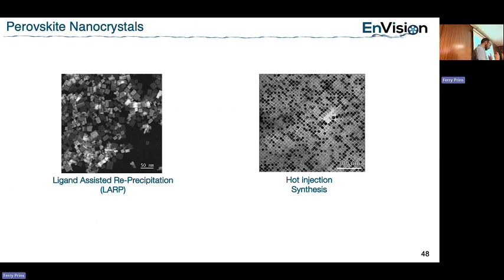There's a motivation to step away from high temperature synthesis of silicon nanoparticles. The way to make good nanoparticles is hot injection synthesis, which again requires high temperature. Same with perovskites - people say they're great because you can do it at room temperature, but if you want really good ones, you need high temperature hot injection synthesis, same as with lead selenide, and then you get perfect particles. That kind of defeats the purpose. If you want something at an industrial level, room temperature and easy, unfortunately what you get is this.